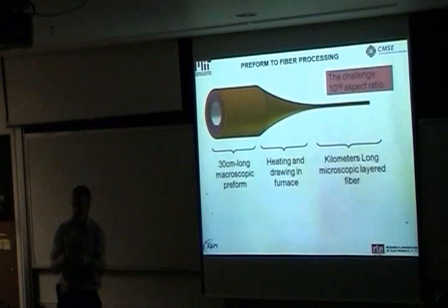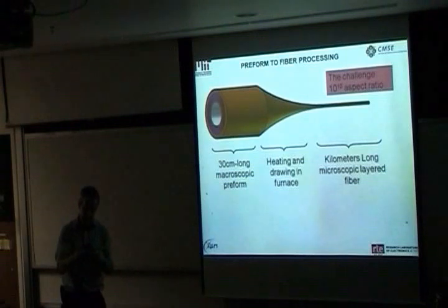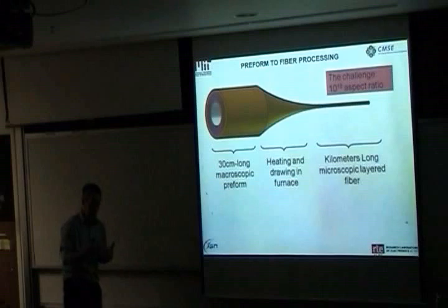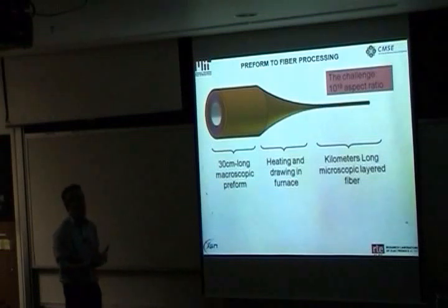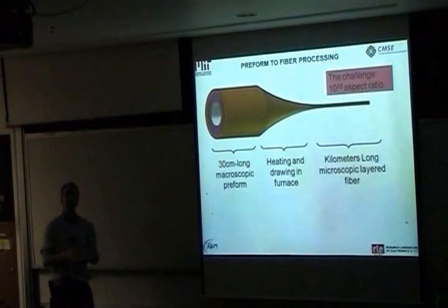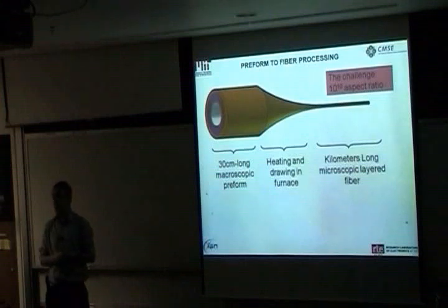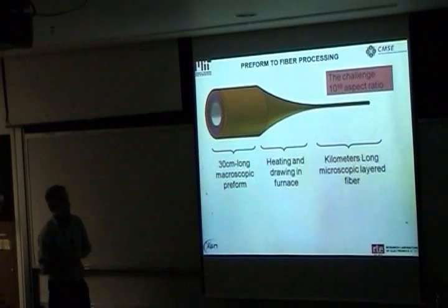What we need to do is make a fiber that has a hollow core. And remember, for these one-dimensional photonic bandgap structures to work, you need the layers to be a quarter of a wavelength. A quarter of a wavelength in the material needs to still be scaled in physical dimensions by a factor of the index of refraction. And so by the time you're making waveguides for 1 micron radiation, it turns out that your layer thicknesses have to be below 100 nanometers, typically, for the types of materials we're using here.